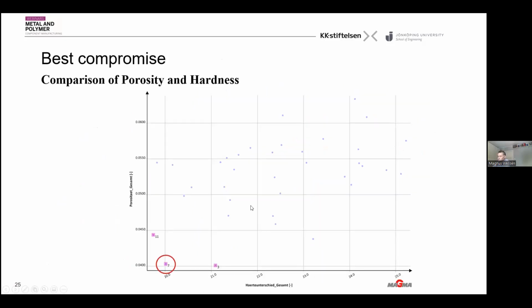In this plot, you see the output values. They have defined the difference in hardness on this axis, and the total pore content on the other. There are lots of dots here, and each dot is one simulation. So you have the designs number 7, 11, and 3, which are the best. You have to decide by yourself. This one has an even lower porosity content than that one, but you have to make your own choice: which is the best one, or should I use that one, because that has lower variation?